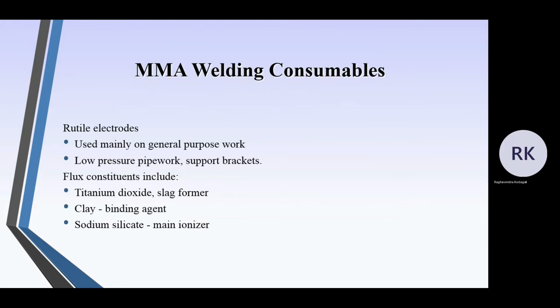Then it comes to MMAW welding consumables. Rutile electrodes are used mainly on general purpose work, low pressure pipe work and support brackets and supports in general. Titanium dioxide is the slag former, clay is the binding agent and sodium silicate is the main ionizer in this.